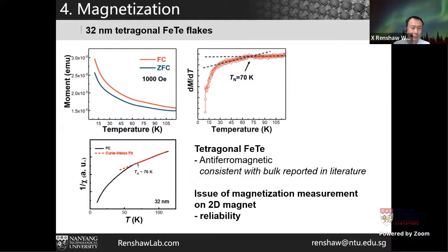But what I want to say is, this is one of the major issues when we study 2D materials within the community by a lot of material scientists. I personally see some literature, for example, either in Advanced Materials or even Nature Communications, when they try to pinpoint what is the magnetic phase of the 2D materials, they measure this and they make claims it's magnetic. But what I want to say is this could also be due to contamination, because the substrate is typically 5x5 or 5x1 millimeters. Then a small amount of contamination would introduce a large magnetic signal in MPMS or magnetization measurements, especially since for 2D materials the volume is super small.